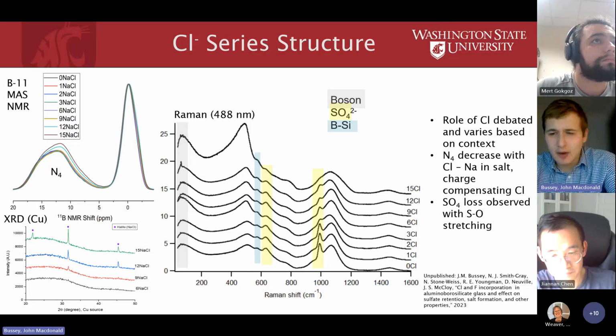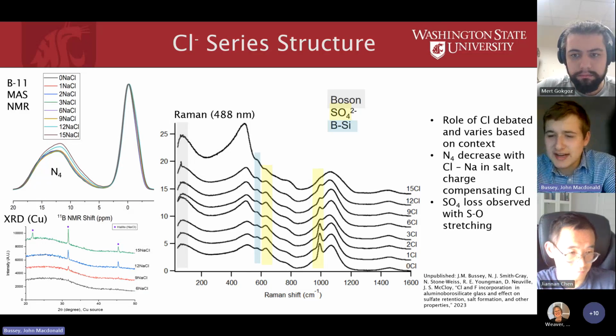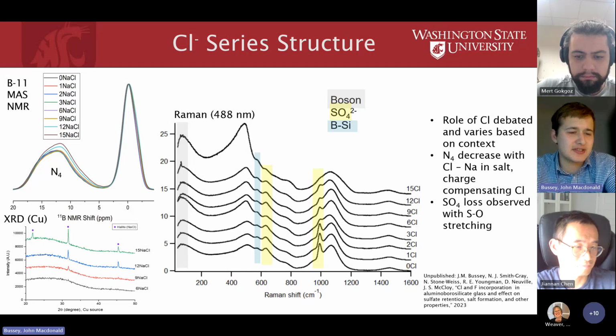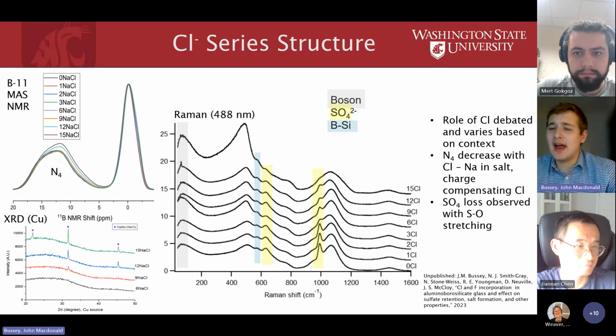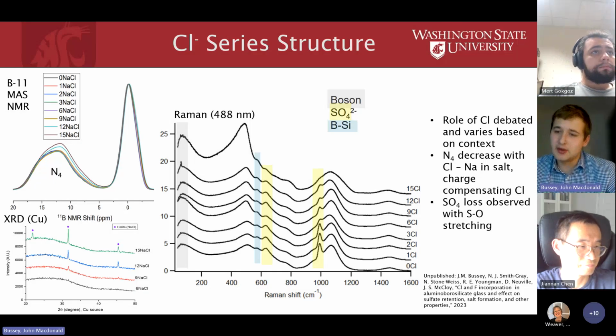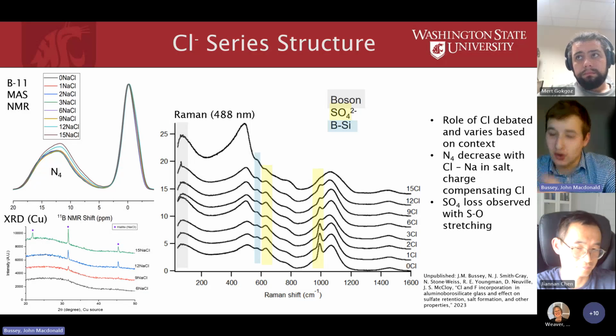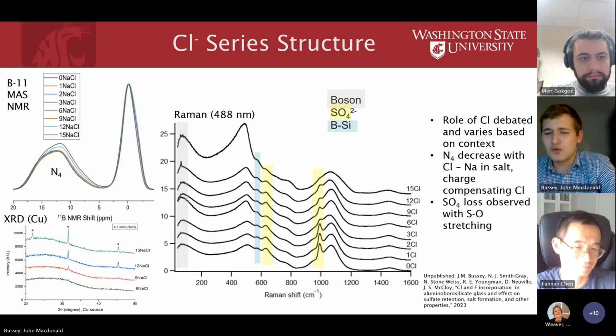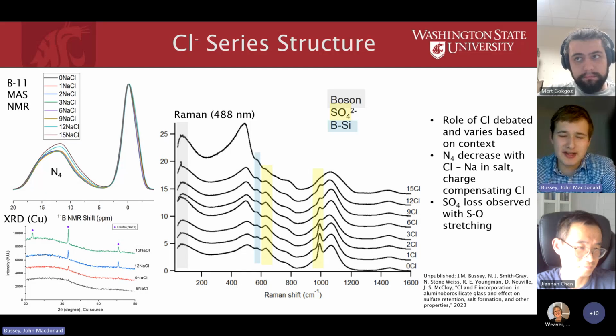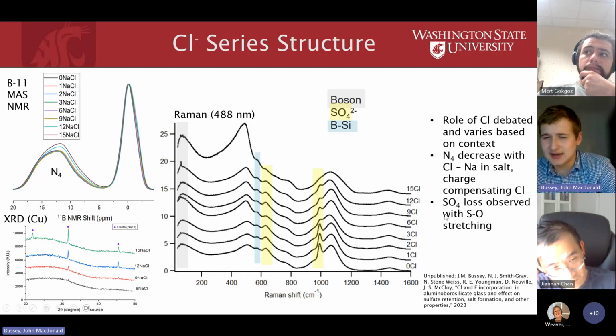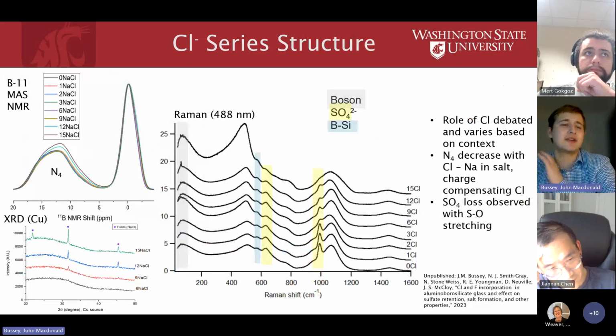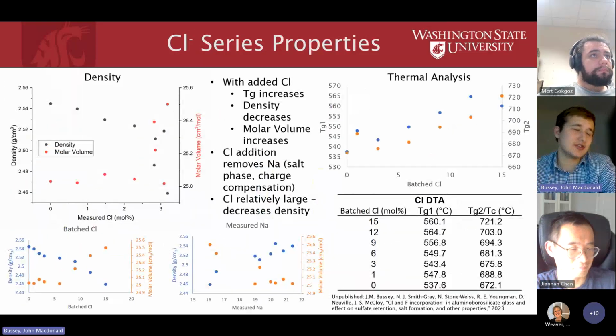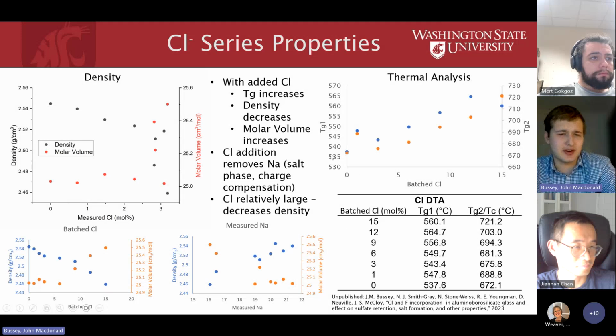In terms of the NMR, we see the N4 peak, which is four-bonded boron, and as that decreases with chlorine, that indicates that there's less sodium available. The sodium in this case is going into the salt, so from this plus the picture before, we get the sense that chlorine and sulfate are both probably leaving the glass into the salt phase, and they're competing for sodium.